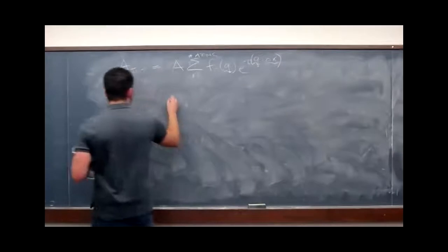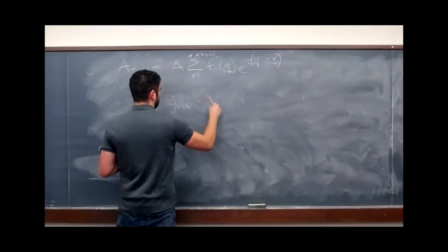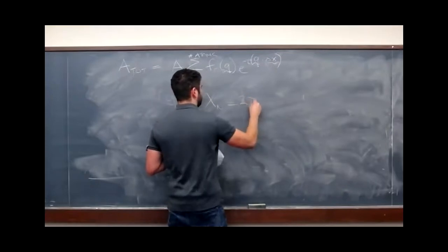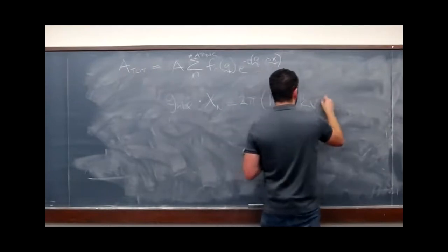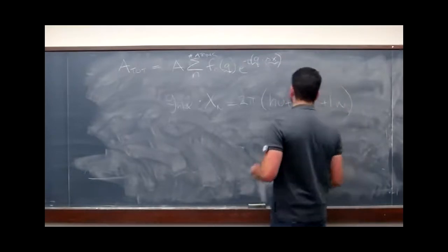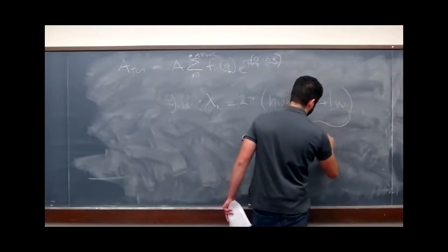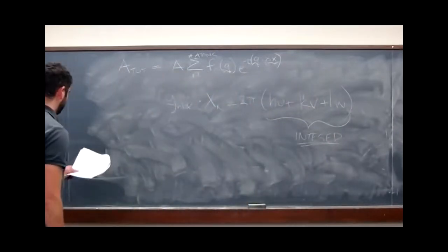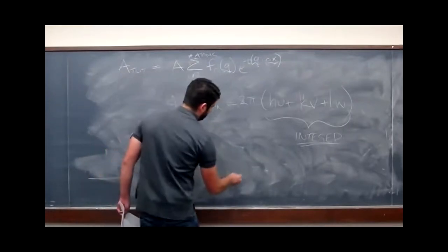And we see that when we multiply a reciprocal lattice vector, we dot it with the unit cell position x, we get 2 pi times (hu plus kv plus lw), which is an integer. So that's it. That is the Laue diffraction condition.